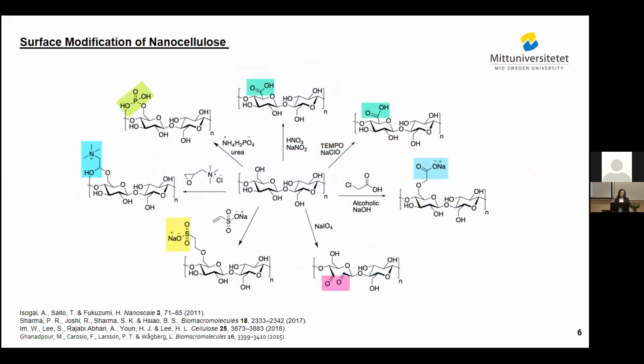Surface modification of nanocellulose can be carried out during the modification and or post-modification. Chemical treatment with TEMPO oxidation, carboxymethylation, sulfoethylation, or phosphorylation is normally used for decreasing the energy consumption during the CNF production. It means that after it is produced, CNF will also be functionalized with these chemicals. And also during the acid hydrolysis with sulfuric acid or carboxylic acid, we will have the functionalized CNC. But today, my topic is about the post-modification.